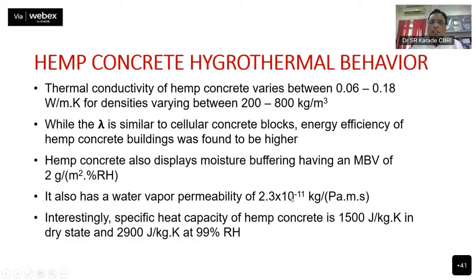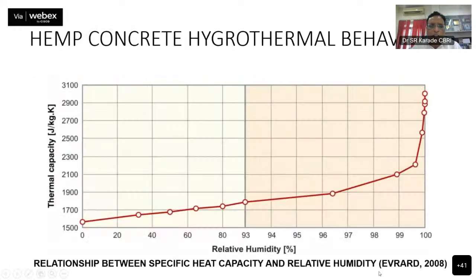Okay. So I was talking about thermal conductivity, which is very low. It's 0.06 to 0.18 watt per meter Kelvin. While the thermal conductivity is similar to cellular concrete blocks, the energy efficiency of hemp concrete buildings is found to be higher because of the hygrothermal behavior of this material, which we can see here.